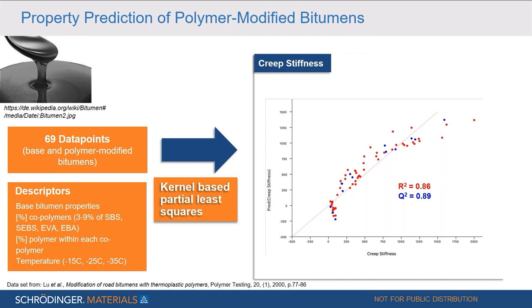And we see here on the right-hand side the linear plot, which shows us the results for the creep stiffness. And the creep stiffness is an important parameter because it's a measure of the thermal stress. If it's so high, cracking will occur. So it's very good to know this parameter. And we see here that we have a very good agreement between predicted creep stiffness and experimental creep stiffness.